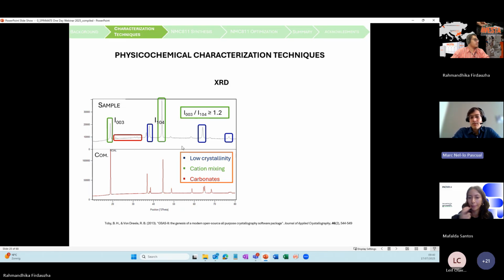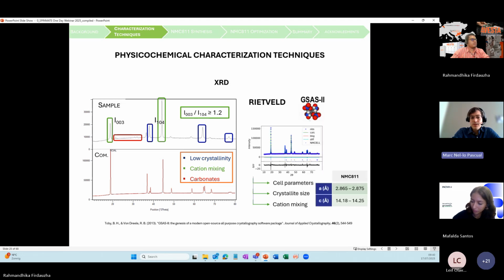But if you go even deeper on this technique, can you go to the next slide? You can refine this data by some open software such as GSAS-II, the one that we used for doing this Rietveld refinement, and you can have a look at further information. And this is to get the cell parameters, these a and c, that should be in this range between 2.86 and 2.87 for the a lattice parameter, and for the c parameter between 14.18 and 14.25. So that's one thing that we can measure with this refinement.